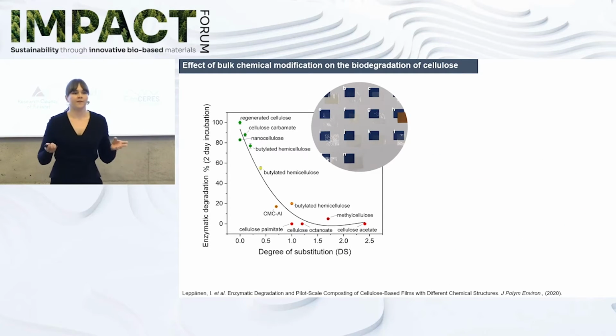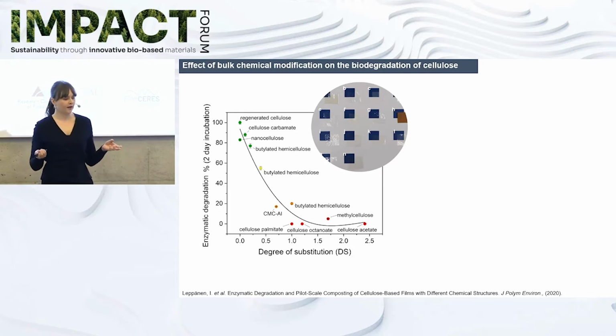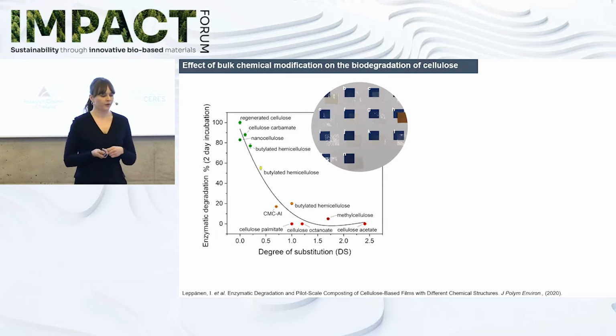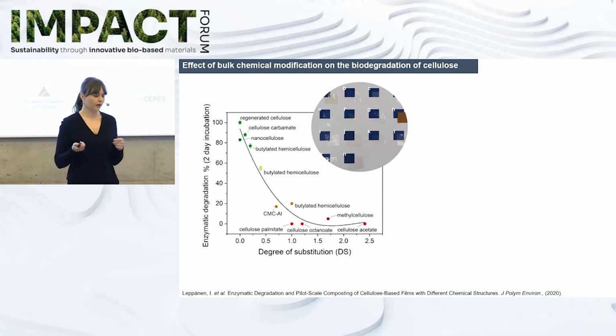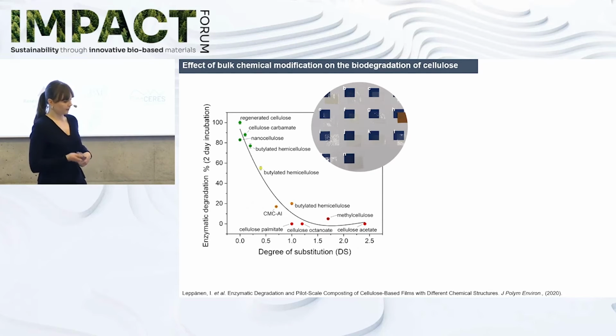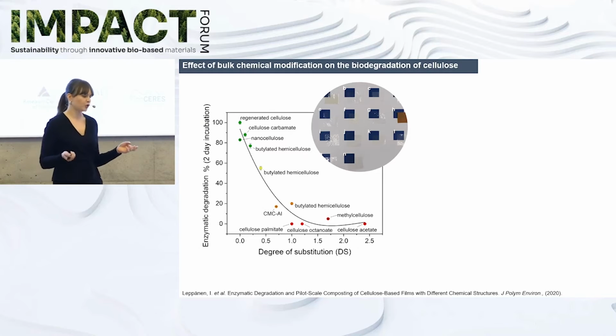So how will the chemical modification affect the biodegradation? Here I will now present the bulk chemical modification. So we have prepared cellulose films from different cellulose derivatives, and they are in the figure there. And then we also have all the films on the graph. So we have done this enzymatic degradation test, which is basically a 2-day incubation with cellulose-degrading enzymes. So it's a mixture that has enzymes that are also found in nature that are known to degrade cellulose.